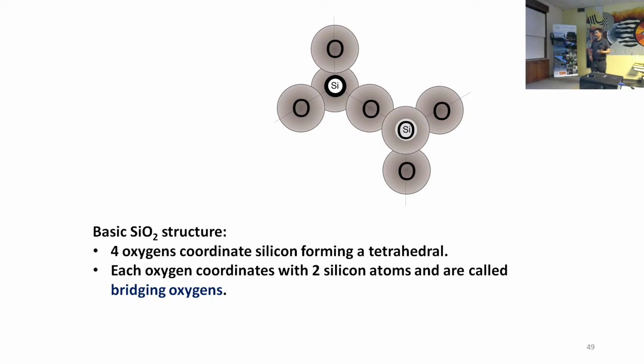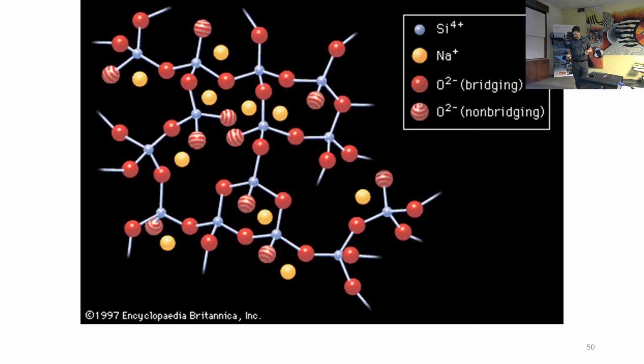What we want to do is to replicate what happens with silica. So with silica, you have covalent bonds between silicon, oxygen, and silicon. This is called bridging oxygen between two silicon atoms. Silica has a very high melting point, around 1,800 degrees Celsius. To decrease this, you have, for instance, sodium, and then you produce the so-called non-bridging oxygens that decrease the melting point to around 1,200 degrees. So the temperatures that we are talking about in silica glass are in the range of thousands of degrees.